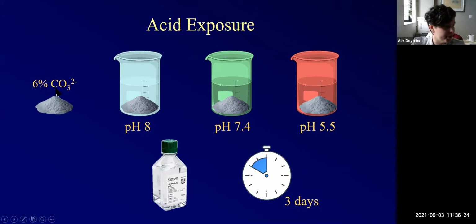We then took this powder and we put it once again in PBS solution. Here we did pH 8, 7.4, and 5.5 to get a basic time point as well. We left them in the solution for 3 days, and then we go back and we try to analyze everything.